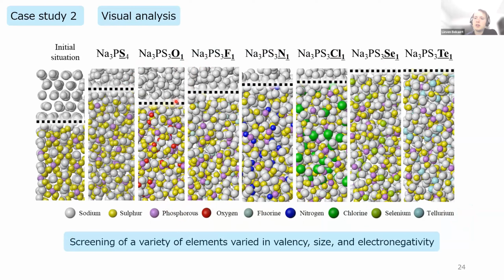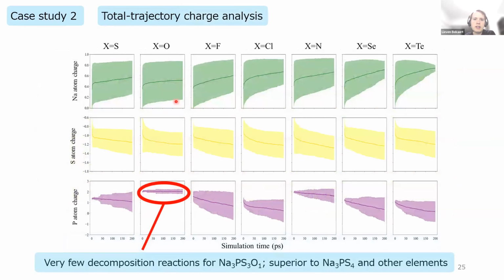But of course, as I mentioned previously, we only get so much information visually. So once again, we use the strength of Matlantis to get the approximate atom charge, and you can then see it in this figure. Once again, plotted for separate atom types, we can see that for oxygen, and especially take a look at the phosphorus atom charge, you find that very little of the phosphorus has decomposed. It shows the standard deviation hasn't changed a lot compared to all of the other materials, which means that this Na3PS3O material has a superior performance to the reference system, so to the material that we studied in the previous paper.